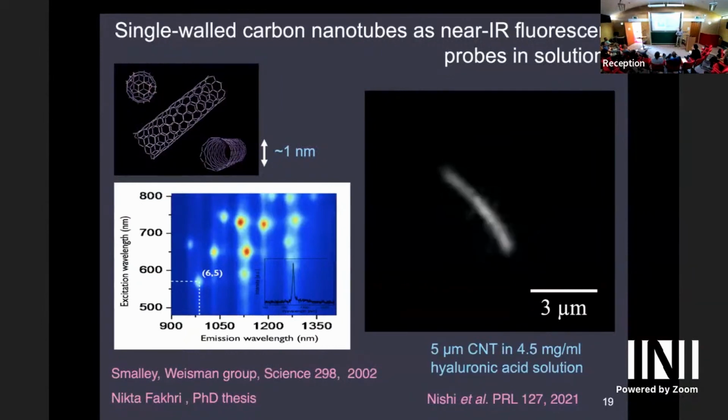They can get into the nucleus. So they don't perturb the biological system, but they also get in very tight places, like agarose gels, where you have a small mesh size, where it's not so easy to have beads, or maybe you can do nanometer beads. But in many places in biology, it's hard to get probes into the system, or they get expelled. Like in the mitotic spindle, if you try to put beads in there, they get pushed out. So these guys are kind of stealth probes.